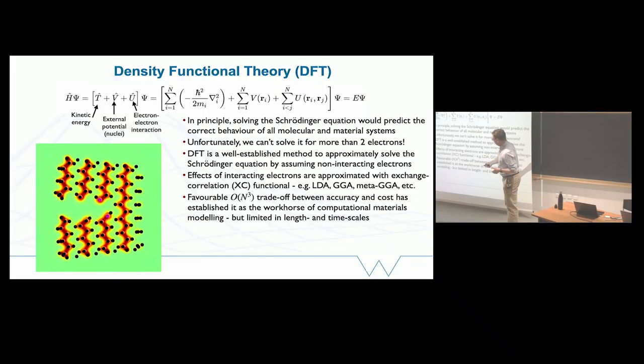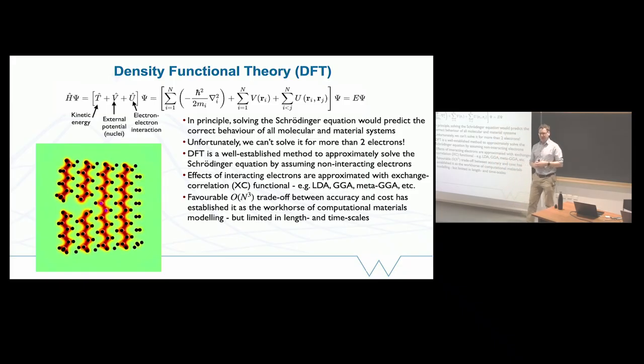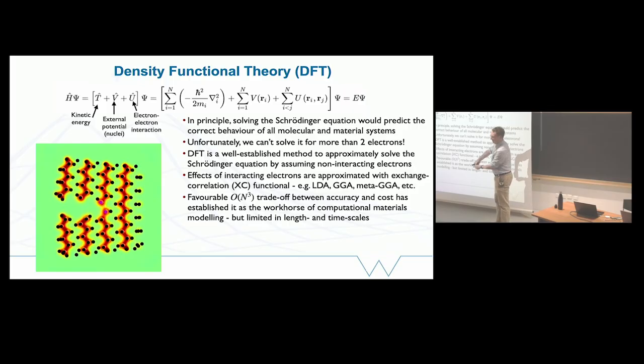Incidentally, what I'm showing you here is that you get more than just energies and forces out of a density functional theory calculation. This is the charge density near the tip of a crack in silicon as I'm pulling it apart. And you can see electrons leaving this bond.